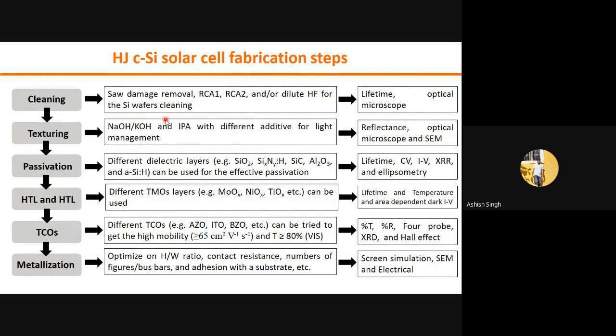Even solar cell manufacturers take wafers from the industry. So what they do, they grow the ingot of single crystal silicon and slice it with wire cutting. During cutting of the wafers, lots of damage happens on the surface of the wafer. Approximately 10 to 15 microns of damage happens on each side, so we need to remove that damage.